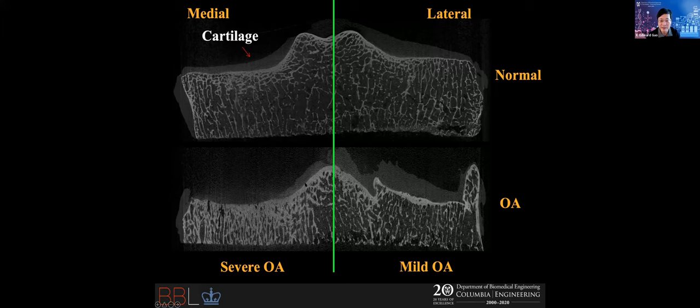And then even though this is X-ray, XCT, you can also see the shadows of cartilage, right? On top of here, you can see there's cartilage really distributed nicely. And therefore in here, definitely on the medial side, they almost lost complete cartilage. But interesting, on the right side, which is the lateral side, they are not normal, okay? Absolutely not normal, because on the right side here you see a thing going up, that's called osteophytes.